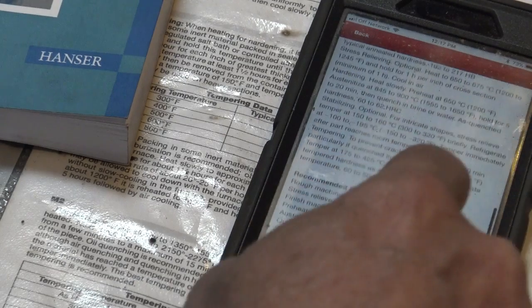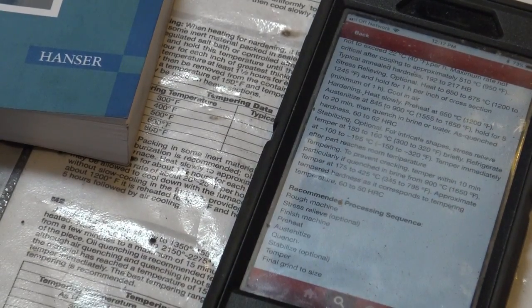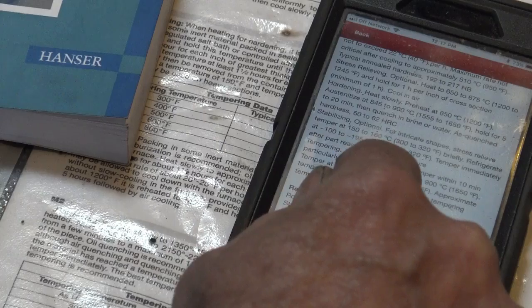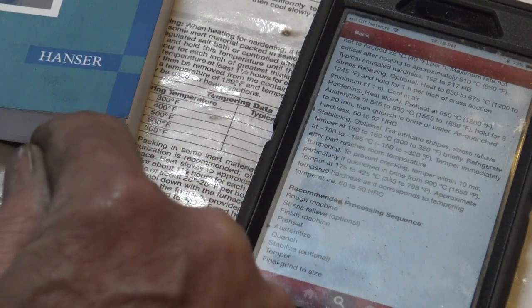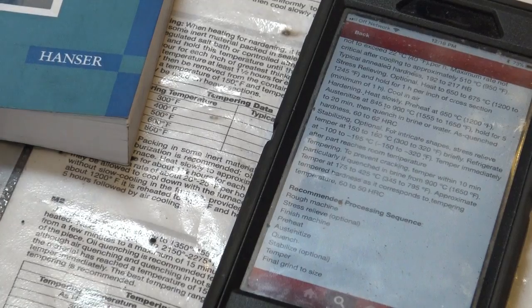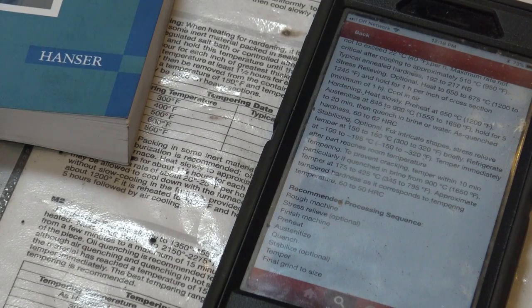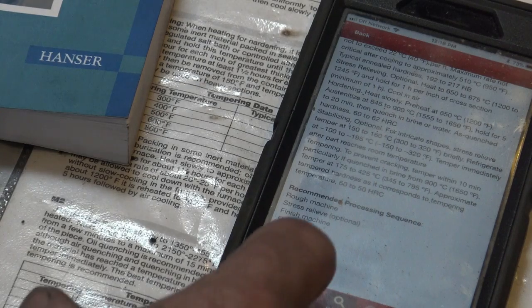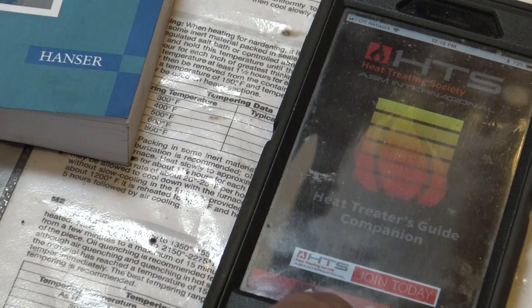The problem with this app is for tempering, it says to prevent cracking, temper within 10 minutes, temper at 345 to 795, and it doesn't tell you what tempering temperature results in what hardness. So it's very vague on the tempering information. And that's one of the things that I would really like to have, more specific tempering guidelines. But it's not a bad app, and every tool steel I've ever looked for is in there. Alloy steels, it's got information on 4140 and 5160 and W1 and O1, and pretty much everything is in there, and it's a pretty handy app.